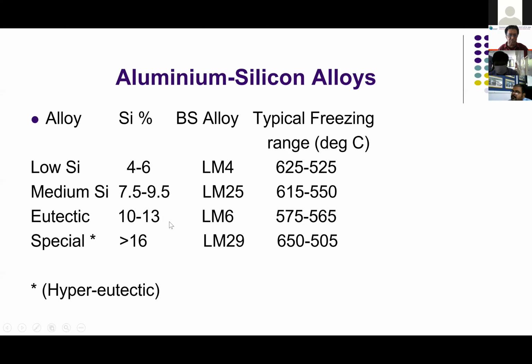This 10 to 13% I'll come to a little bit later. I would always suggest that silicon should be maintained below 12. I'll come back to that reason later. There are some alloys using more than 16% silicon, piston alloys.